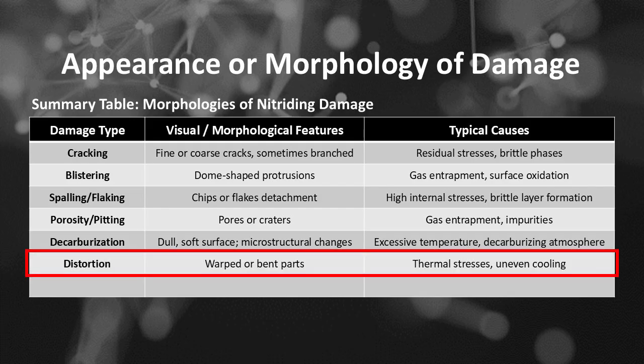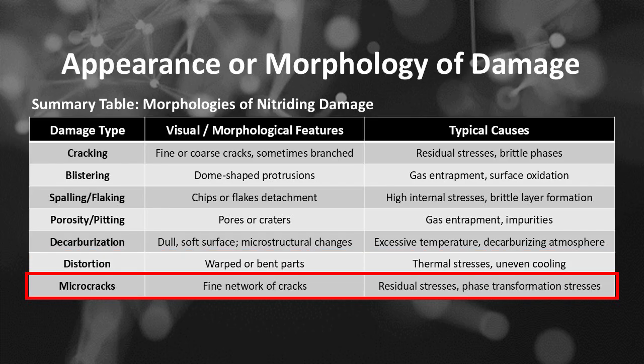For damage type distortion, the features will be warped or bent parts, and the typical causes will be thermal stresses and uneven cooling. For damage type microcracks, the features will be a fine network of cracks, and the typical causes will be residual stresses and phase transformation stresses.